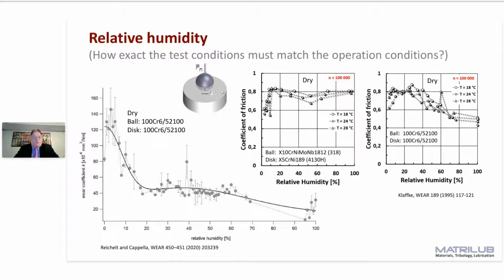So not only to have constant and defined test conditions, you should at least measure the relative humidity, but also if you want to apply your results to an application, you should know the impact of humidity on your friction couple. Otherwise, you will have claims from customers saying it is not working, and other customers don't complain. And the reason was simple, that friction and wear depend on the humidity.